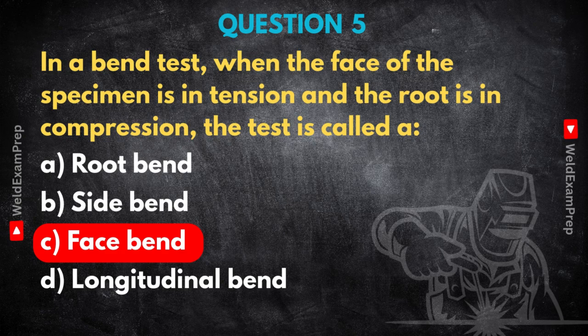If the sample passes a face bend test, it shows the weld metal and its immediate surroundings can deform significantly without fracturing. And that's a critical indicator of its integrity, its ability to perform under stress in service. Right, so the key insight is that a face bend test is a direct, powerful way to check the ductility and soundness of the weld's outer surface when it's being pulled apart. It reveals hidden defects and confirms the weld can bend without catastrophic failure. A really fundamental check for quality assurance.